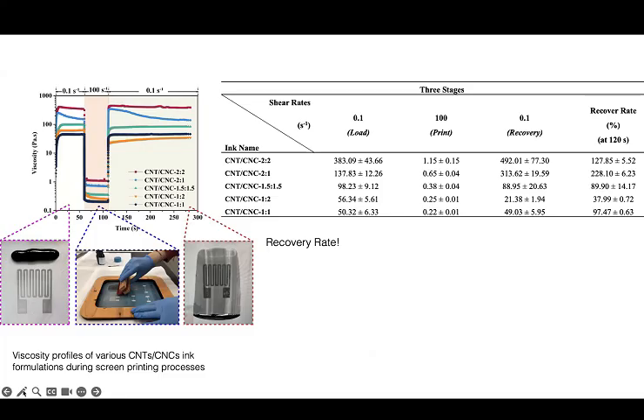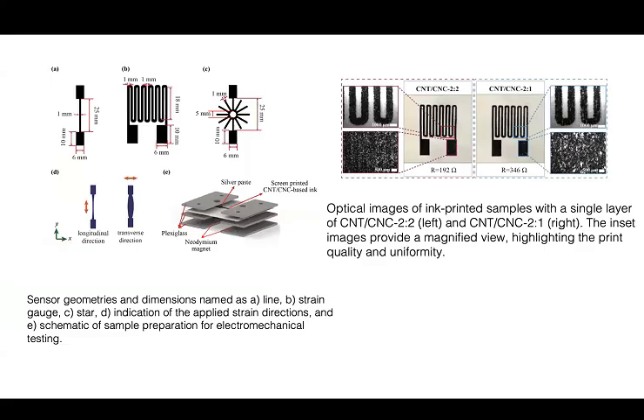There's a drastic drop in the viscosity, which makes the dispersion, the suspension, quite fluid. Then you pull it through the geometry that you want. This is the second phase. The ink itself needs to recover. If it spreads, you can't get the tiny details of these transmission lines. You would remember the previous examples of the antenna structures, where there were some defects in the structures. We are trying to avoid that, and we do that by understanding the composition. But the body itself is also complex. Breathing gives you a strain level of around 5 to 10%.